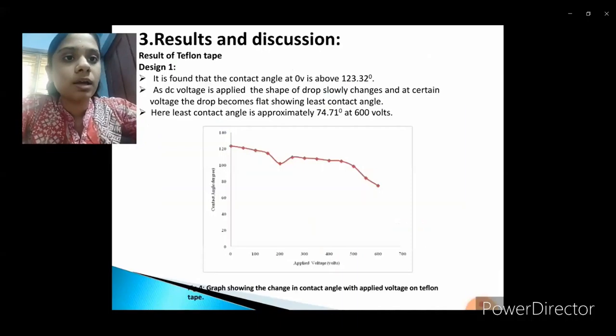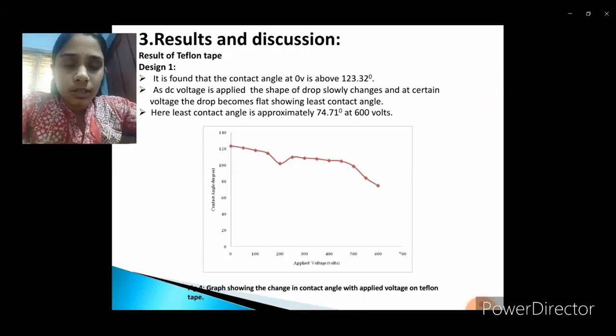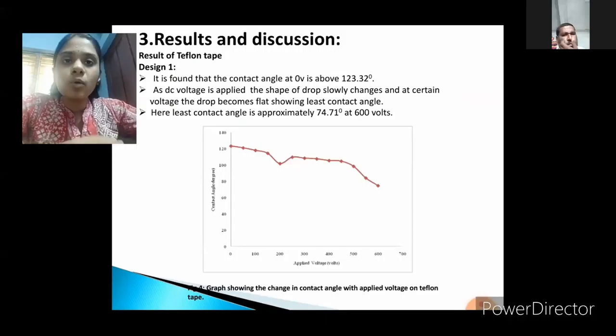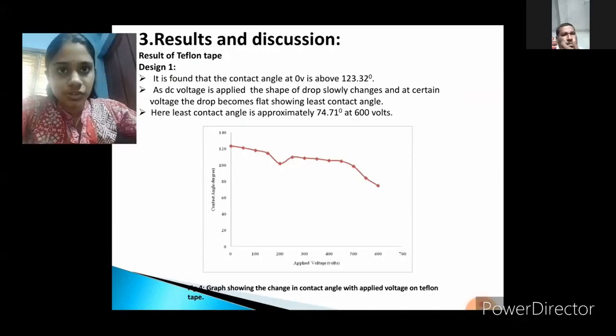Now, the result on Teflon tape, that is the first substrate that we have used. At 0 volts, when the voltage is not applied and there is no electric field, the contact angle is found to be 123.32 degrees. Now, as we go on increasing the applied voltage, the shape of the drop changes, and as a result the contact angle also changes. The contact angle starts decreasing, and at maximum voltage it is the least contact angle. So the least contact angle on Teflon tape is found to be 74.71 degrees at 600 volts, and this is the graph plotted. The second one is the result on the thin polytetrafluoroethylene membrane.